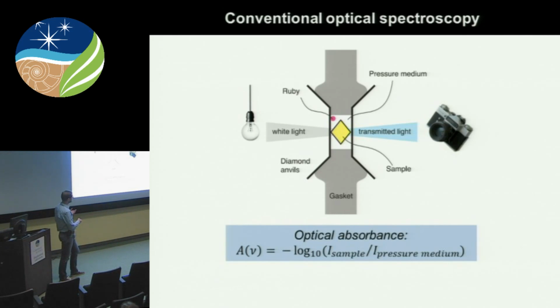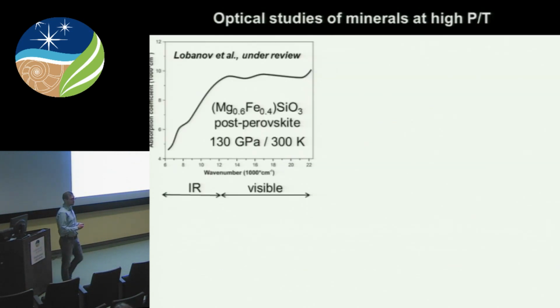So you have a light source that emits some white light that illuminates the sample. Then you collect the transmitted portion of this radiation with a detector of sorts. And then you compare this transmitted light through the sample against the transmitted portion of the light collected through the pressure medium. Basically using this decimal log, you get what we call an absorption function, or simply a spectrum. So here is an example of an optical absorption spectrum of post-perovskite at 130 GPa at room